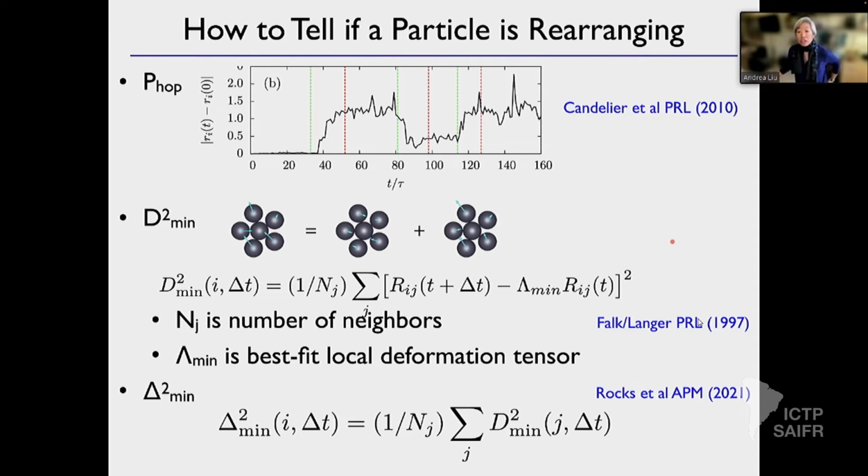Yeah, so you can look at the stresses, which is like the first derivative of the potential. You can look at the Hessian, the second derivative of the potential, or the third derivative. People have looked at nonlinear derivatives, and you can come up with good predictors. We're avoiding that because we don't want to have to know the potential, because we want to be able to apply this to experiments. So that's why we're only looking at structure.